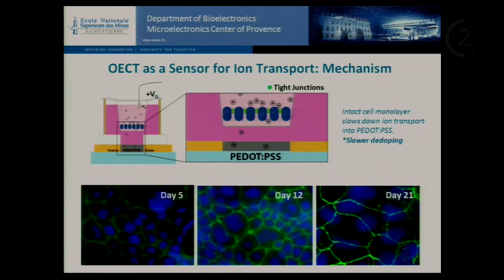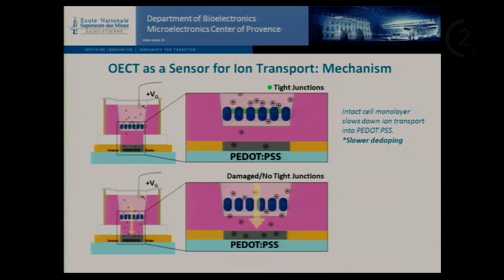We get a slower de-doping in the device. If we then damage these tight junctions, or these tight junctions aren't present, there is no ionic barrier to transport between the gate electrode and the polymer channel. De-doping is faster, device response time is faster.